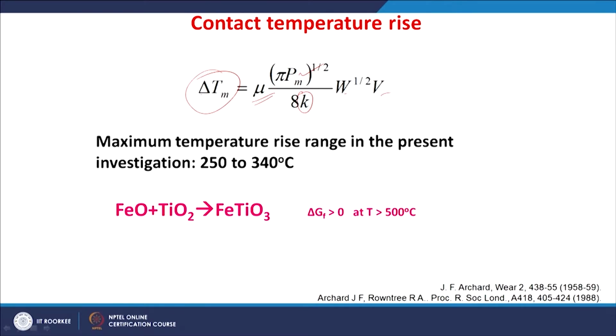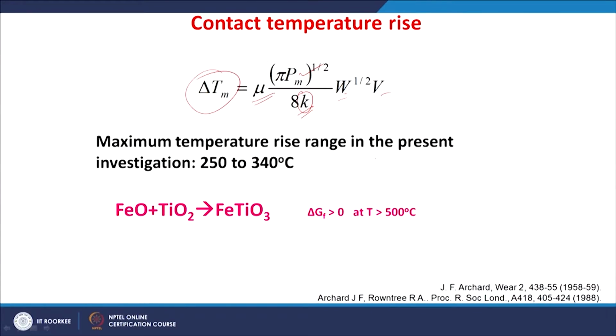So, using the data for the cermets used in the present investigation, the thermal conductivity was determined by the rule of mixture, and all the other values we know: the maximum stress, the load and the velocity. So, by incorporating all these values along with the respective friction coefficients, the temperature rise in the present investigation was found to be from 250 to 340 Celsius based on the cermet compositions at the highest load of 50 Newton.